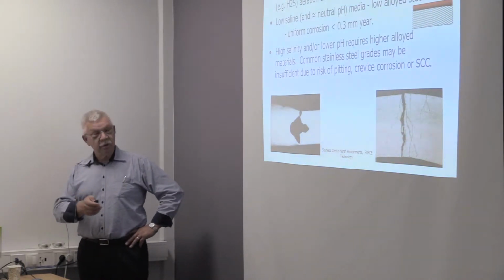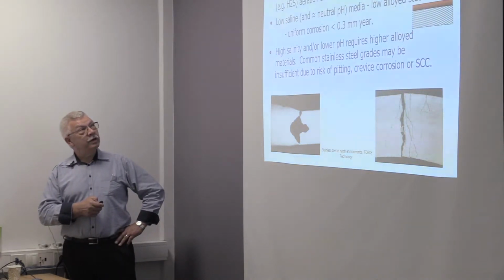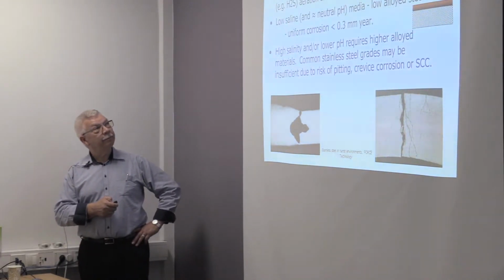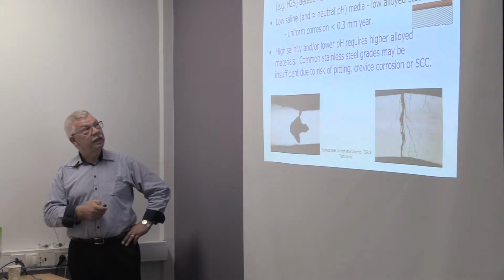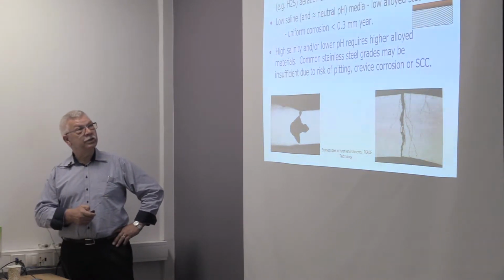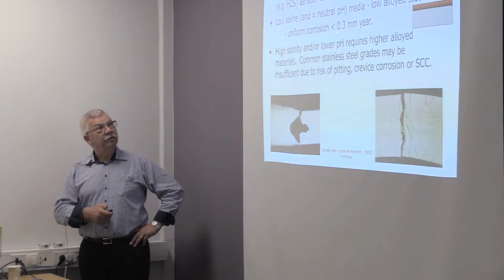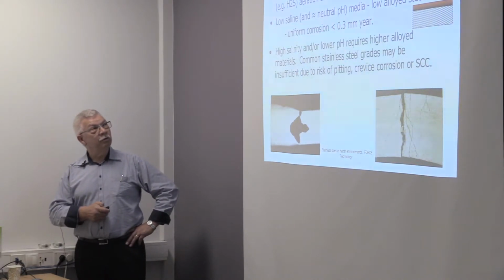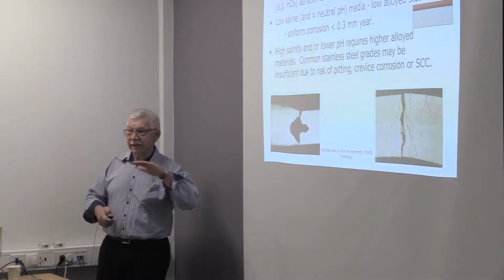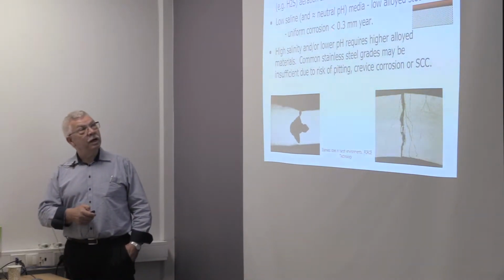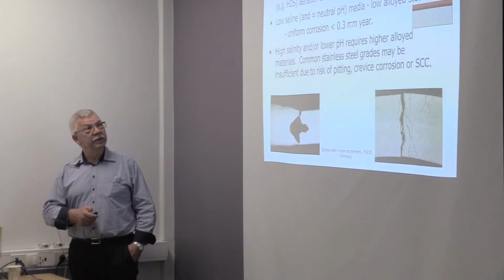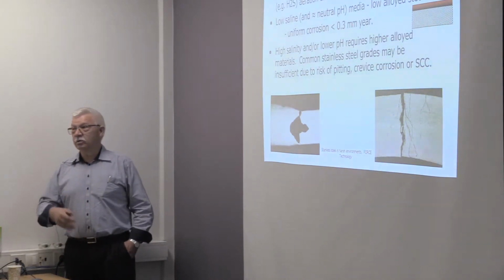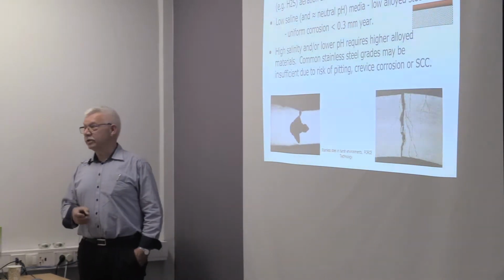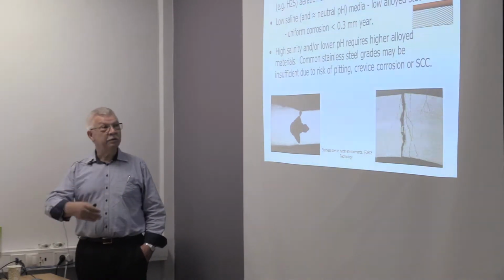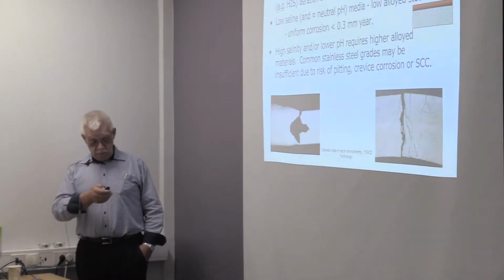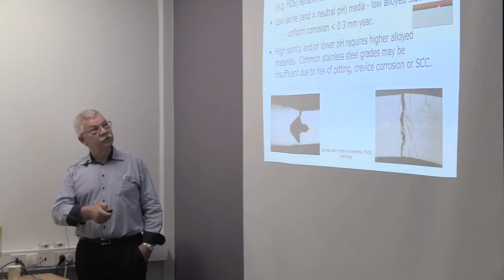If we have conditions with very low salt content and approximately neutral pH, then we have very little corrosion. Uniform corrosion means that we lose a little of the surface all the time, but below 0.3 millimeters per year. So you can control that by adding a little more wall thickness in your system, and you will be okay for a number of years. So low alloyed steel is what we can use there.